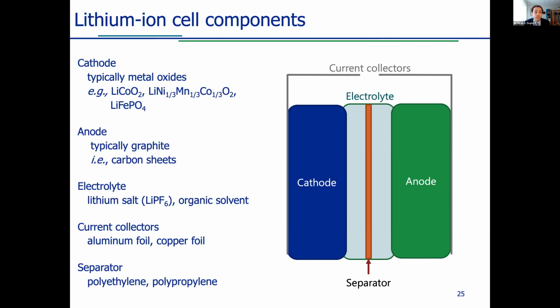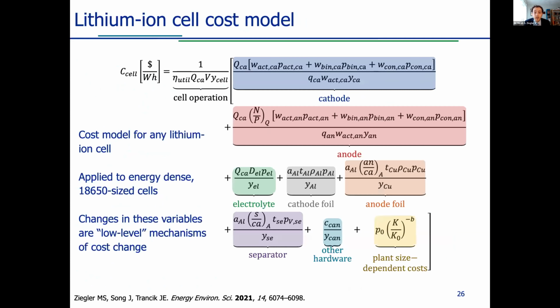That help comes in the form of the electrolyte, which is typically a lithium salt like lithium hexafluorophosphate, dissolved in a mixture of organic carbonates. We also have current collectors to help the electrons move back and forth, and they are typically aluminum and copper foil. And then we need to keep the cathode and anode separate with, well, a separator, which is typically made out of polyethylene or polypropylene, sometimes with a coating on top. So given all of this information, as well as more details as to what goes into these components and how the batteries are manufactured, we can set up our cost model for lithium-ion batteries, which I'm showing here.